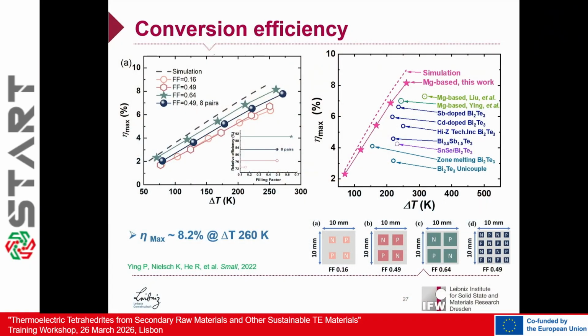This was done in this study, where we varied the filling factor and also played a bit around with a different configuration, instead of a 2 times 2 configuration, a 4 times 4 configuration. And when we do this, you can see here, when we come to the highest filling factor, 64%, we also have the highest efficiency. So there's a more than 1% gain, about 8.2% efficiency, when we apply a temperature gradient of 260 Kelvin, for example.